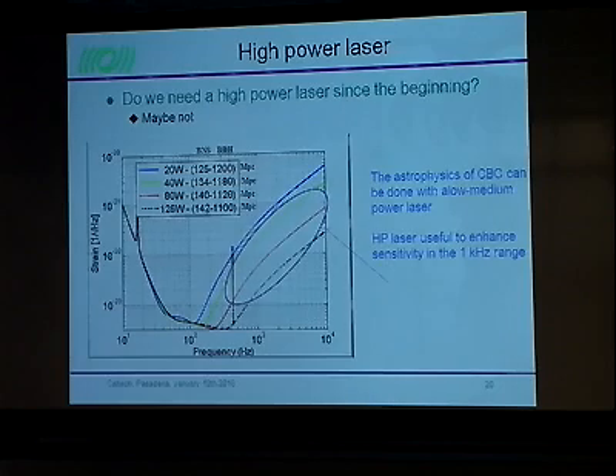It should be noted that probably we don't need a high power laser since the beginning. Here is a picture showing the sensitivity of this detector as a function of power. What is shown here is the range that you can reach in terms of binary neutron star and binary black holes as you go up in power. So you see that decreasing the power down to 10 watts to 20 watts only loses a small factor of horizon in terms of binary neutron star and actually improves a bit the binary black hole range. So in the end, for this physics, the cost is not too much.